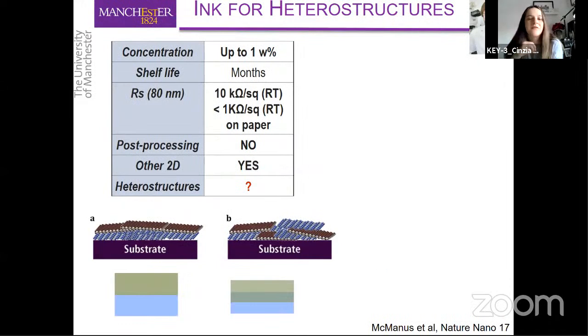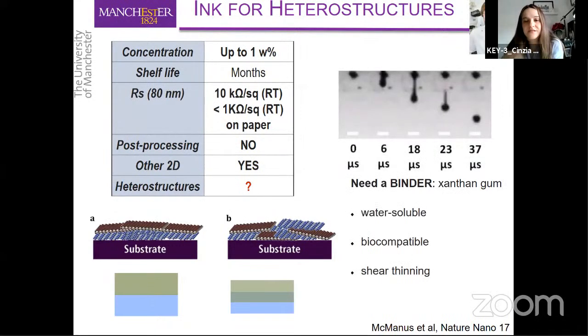However, we are still not ready to make fully printed heterostructures because, as I mentioned to you, there is another problem that we need to mitigate, which is the intermixing of the material at the interface. And this again can be mitigated by applying formulation engineering, and in particular by adding a binder in the dispersion. So in our case, we decided to use xanthan gum because it's water soluble, it's biocompatible, and shows a very strong shear thinning effect, which is exactly what we want here, because this effect will minimize the diffusion of the flakes, and therefore will minimize this intermixing at the